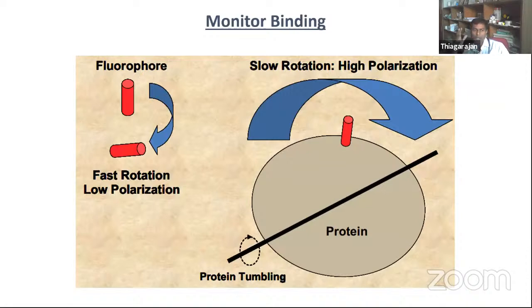Normally this kind of anisotropy is very useful when we deal with biomolecules like proteins and enzymes, because these proteins and enzymes rotate very slowly. But for organic molecules we cannot do any anisotropy because they rotate very fast. We cannot get any anisotropy from it. But when we have a biomolecule, it's big. When we excite it, it rotates very slowly. So when we record in the parallel or perpendicular direction, we will get different intensities. From this, we can determine a lot of factors about these biomolecules.